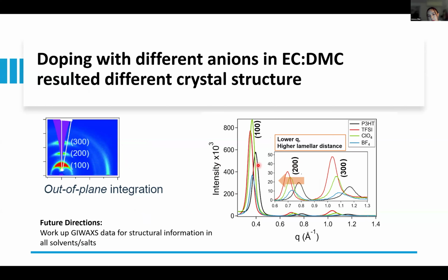So we can see that upon doping, all three of them are shifting to the left, so to greater distances than the intrinsic lamellar spacing of P3HT. And it's confirmed that TFSI is increasing the distance the most because it's the largest, followed by perchlorate, followed by BF4 in blue here. But this is all done at one doping level, and in our future directions, we want to get data for various salt and solvent pairs at different doping levels so that we can really see what's going on at each peak in the CV.